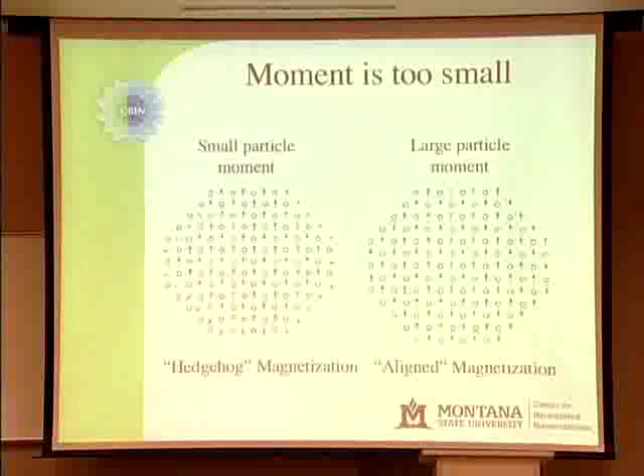else. When I put a coating on the outside, I, in a sense, give them a neighbor. I fix this coordination, I increase it, and the chemistry is now generating a bonding that is going to satisfy the surface anisotropy, and now it does what the other people say, which is point upwards instead of pointing outwards. But the coat is not magnetic. You're right, the coat is not magnetic, so the interaction is chemical rather than a magnetic interaction.